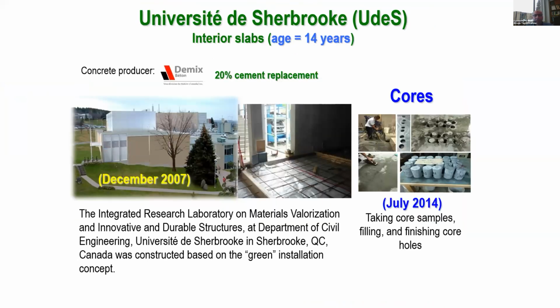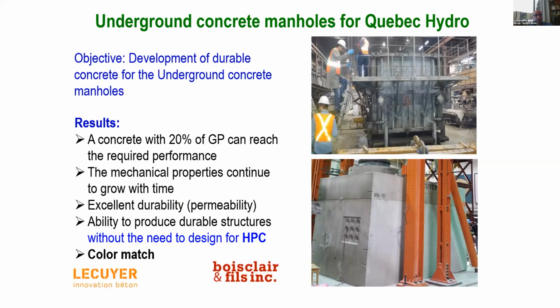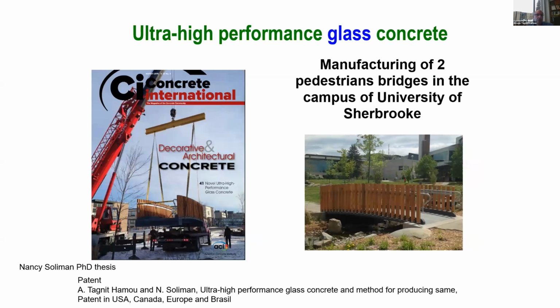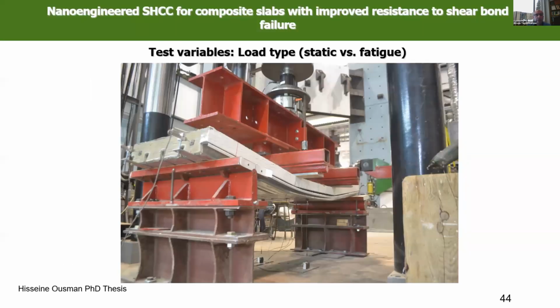and the slabs at the University of Sherbrooke also, where we used the chance when we constructed the laboratory. The manholes of Quebec Hydro now are more and more designed with the glass powder up to 20%, and they are testing the real structures actually. We also developed the ultra high performance glass concrete, and we have a patent thanks to the work done by Nancy on her PhD thesis. And this is actually owned by a big company.